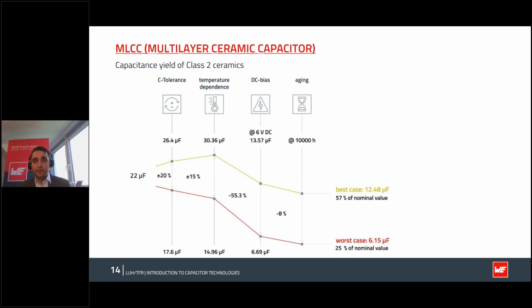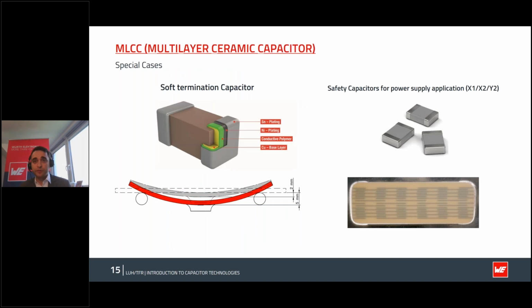Apart from that, there are some special MLCC types here I'd like to mention. If you ever have a failure for an MLCC, the most common failure is internal cracking. It's quite hard to see as this can be microscopic fractures. For that, we have a soft termination or flex caps. They have a conductive polymer, you see in green here, which can balance some internal tension and bending and also vibrations.